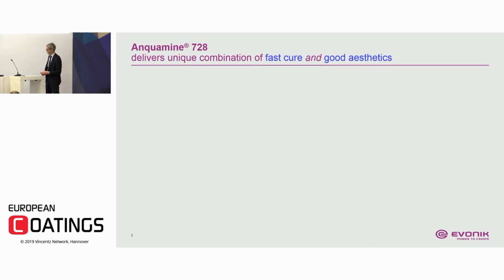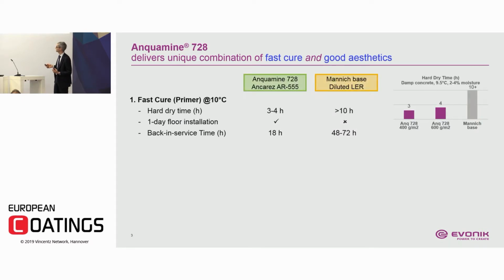So the product, as I mentioned, has two key features. On the one hand, it delivers very fast cure speed. What's displayed over here is a comparison of the 728 with solid epoxy resin dispersion in comparison to a Mannich base with a liquid epoxy resin, which is a very conventional system nowadays to cure fast epoxy primers. And you see that in case of the ANQUAMINE 728, you get a cure speed of about 4 hours. With a Mannich base, you're talking about 10 to 12 hours at 10 degrees.